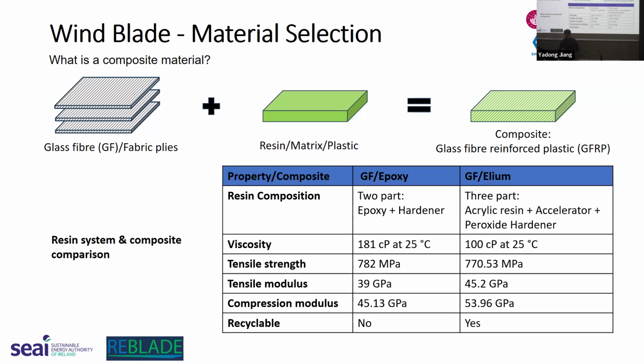The viscosity is quite similar, although the Elium resin has a lower viscosity, which is more beneficial for infusion. It can penetrate fibers much easier than a higher viscosity resin, such as the epoxy, although they're fine. Tensile strength is very, very similar, as well as the tensile modulus and compression modulus. They're all around the same values. One has a higher tensile strength but a lower modulus, and similar for the compression modulus.